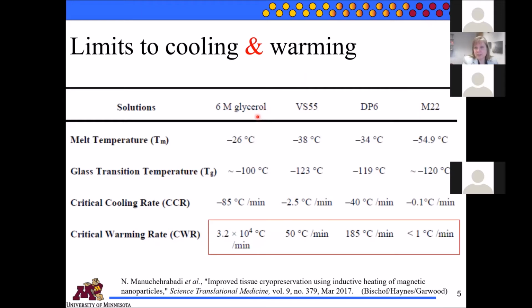They have certain properties that have to be met. So first they have to melt at a decent temperature. And then also there is the glass transition temperature. So you have to get above this temperature at this critical warming rate. They've mastered this critical cooling rate pretty well, how fast you have to cool it. Glycerol, that's why you can't just put in glycerol and freeze it right away. You have to do it fast and uniformly freezing.